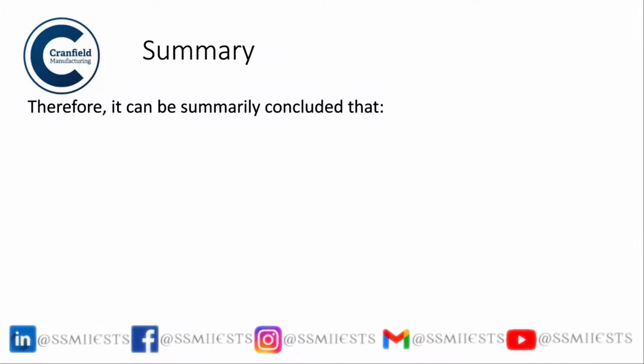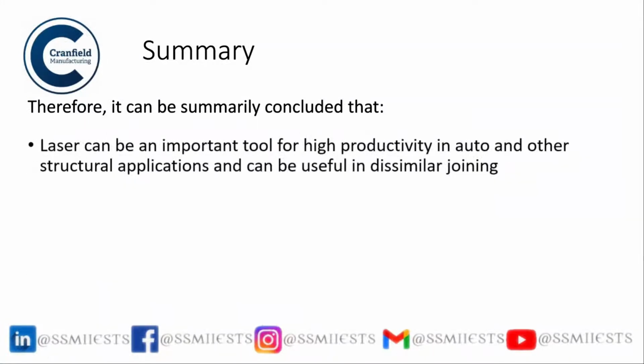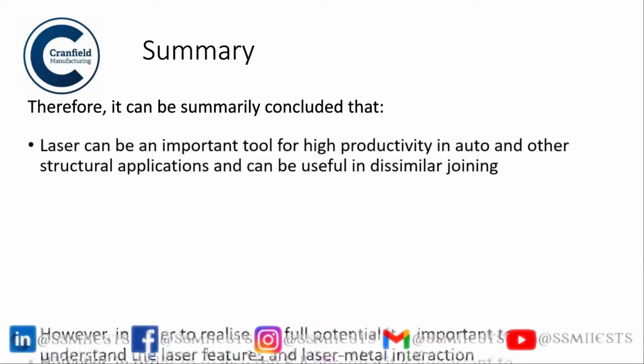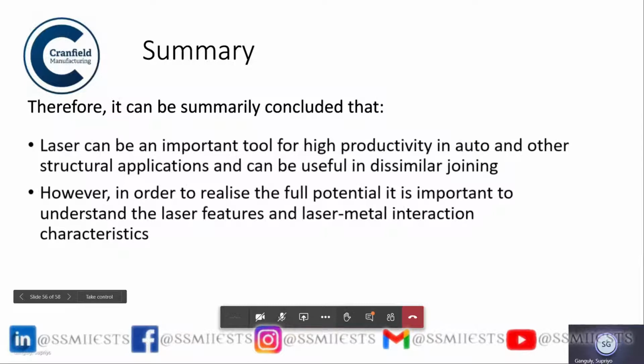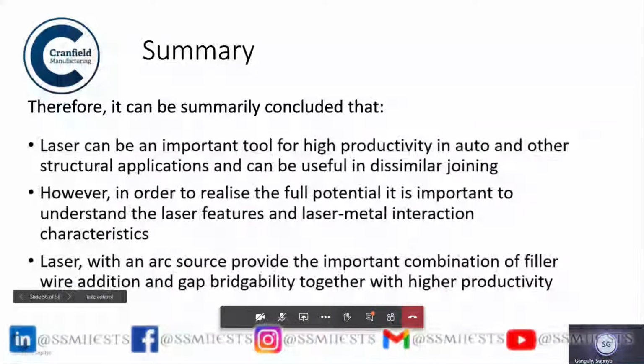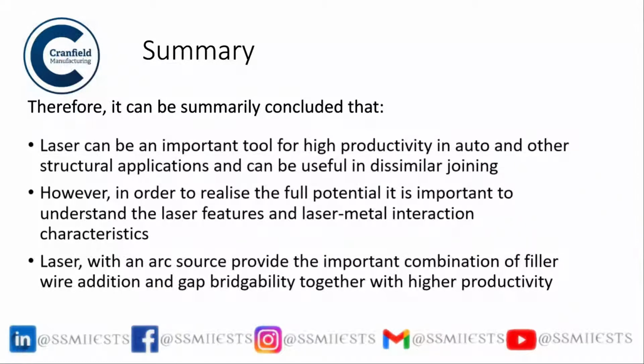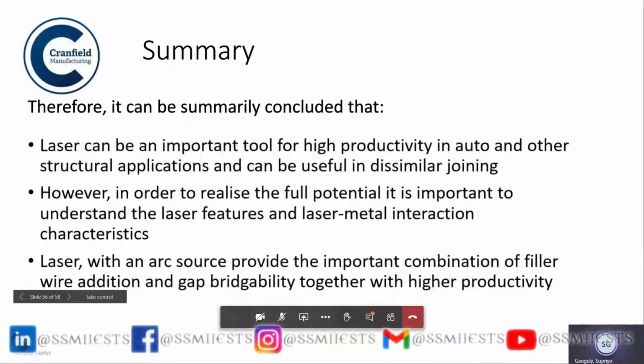homogenized weld. So in summary, I have to say that laser is an important tool for high productivity in automotive and other structural applications and can be useful for dissimilar joining. However, in order to realize the full potential, it is important to understand the laser feature and the corresponding laser metal interaction characteristics to apply it in an intelligent manner. And for high productivity, high thickness or large dimension structurals, laser and arc can provide a very important combination to achieve filler wire addition as well as gap bridging ability in order to realize the full potential with regards to the productivity of the process.